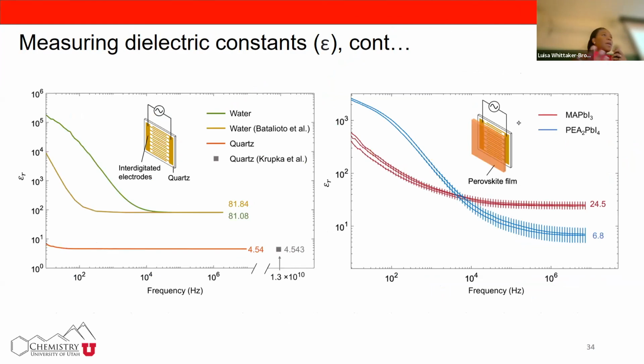Okay, so we designed the experiment. We just did some standards here. So this is quartz. We're not going to see that much of a difference. But then this is getting the dielectric constant of water. And these are different waters, right, with different ions in there. And that's why you see that this is different. Okay. So then on the other end, we have our perovskite film. So this is 3D, right? Then this is 2D that has a lower dielectric constant, which for the DFT is given as 6.8. So that is the bulk dielectric constant, right?